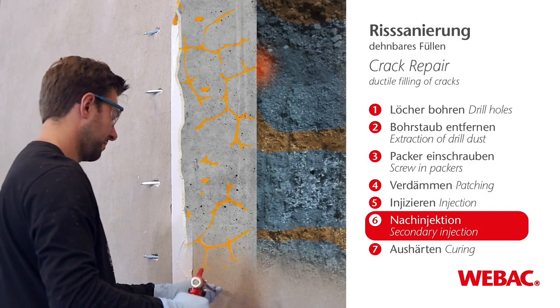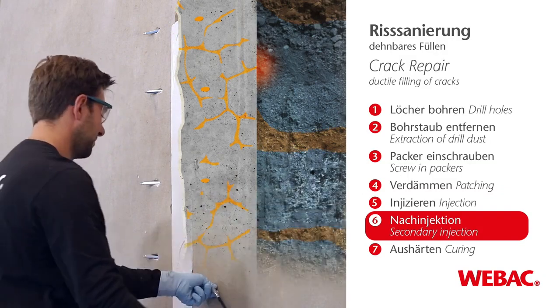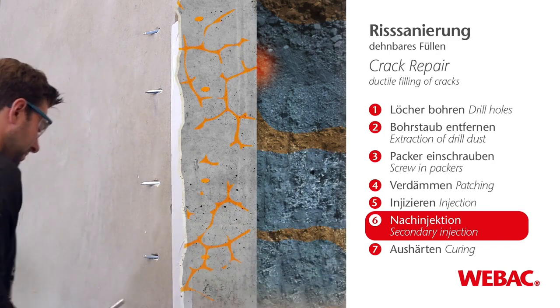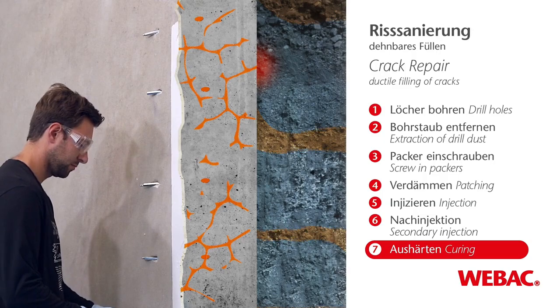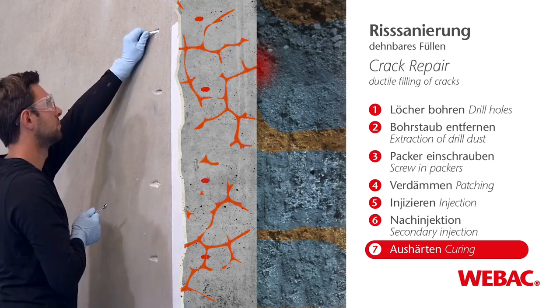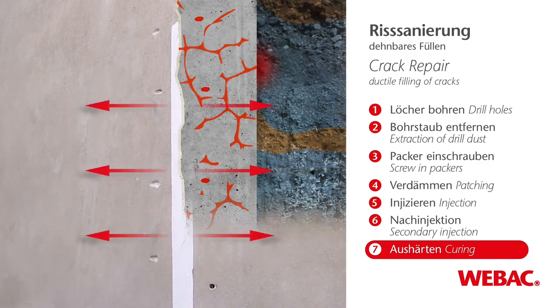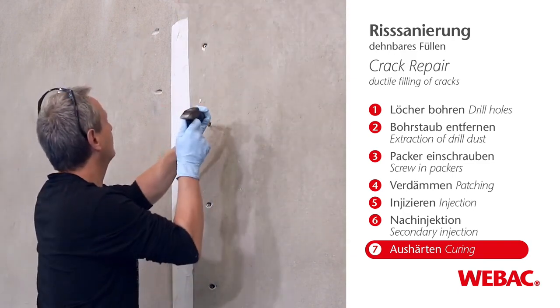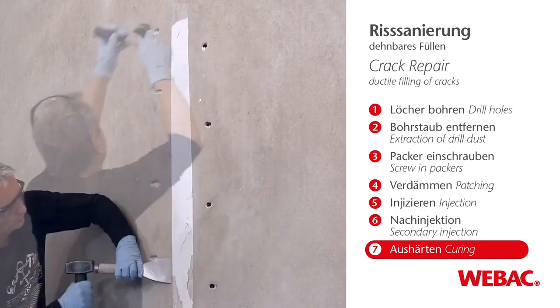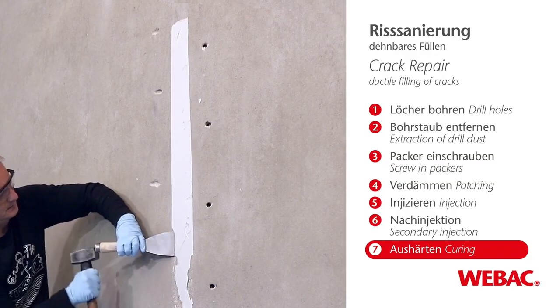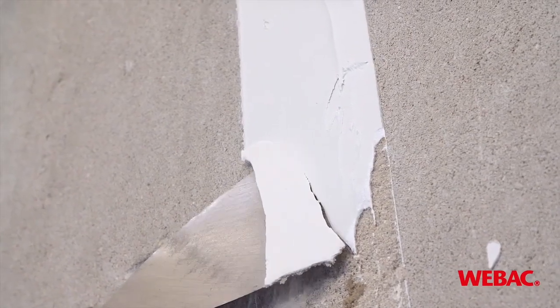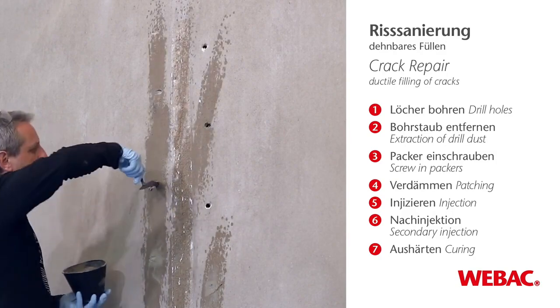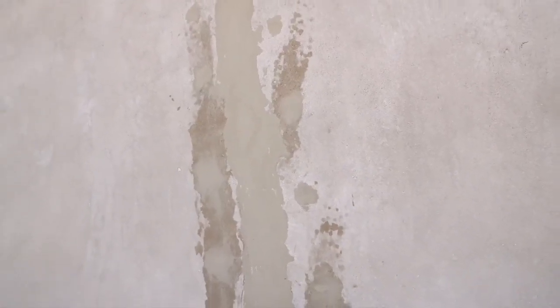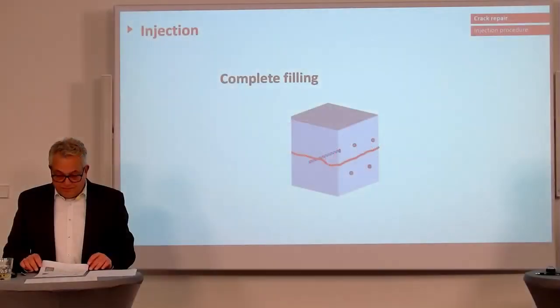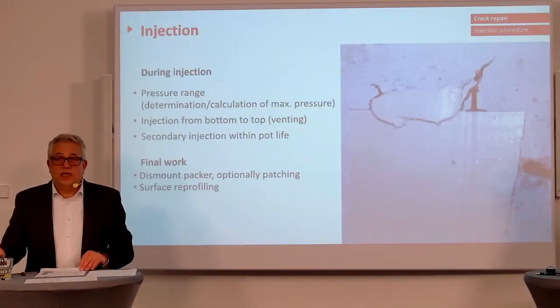at the top. Very important is a secondary injection, because due to gravity, the material gets sucked into the finest fissures, and if you are injecting from the bottom to the top, this re-injection is essential. Removing the patching, and make the surface nice and even again. Okay.